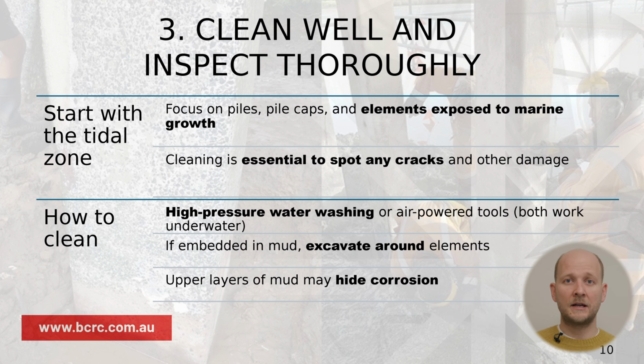I would recommend high pressure water washing or even air power tools. Both of these methods work well underwater, and you do need to clean underwater sometimes, not very deep, but I'm talking about 200, 300, sometimes 400 millimeters deep to look at your pile a bit closer. Corrosion can extend underwater, especially in a tidal environment. If your element is embedded in mud, it's also worth excavating the top layer and making sure to inspect it.